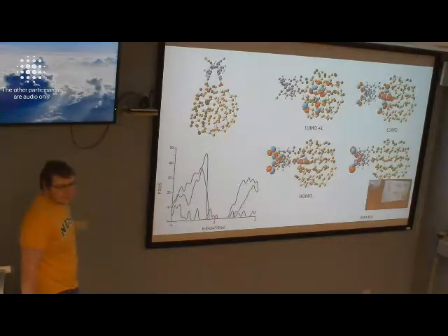And this might also be the answer to the question of why the gap is closed. I'm pretty sure that you probably have this state not appearing in the gap for your pristine Janus quantum dot. So we need isolated structures also to compare one by one and look at the orbitals.